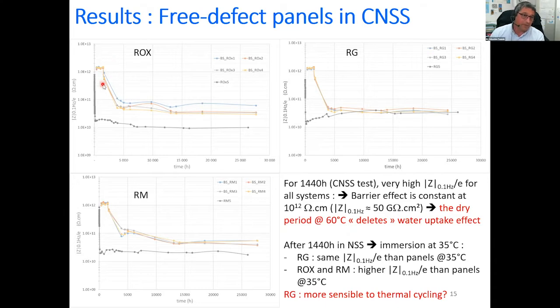But after the test in salt spray, the panels were immersed in the sodium chloride solution at 35 degrees C, and then we can observe a continuous decrease of the reduced impedance modulus, showing a decrease of the barrier effect. And this decrease seems, however, lower than the one that was observed in the aquarium at 35 degrees C. This is true for ROX system and RM system. But for RG system, we've got the similar values of the reduced impedance modulus, showing that maybe here RG was more sensible to this immersion in solution after the salt spray. So maybe RG is more sensible to thermal cycling.